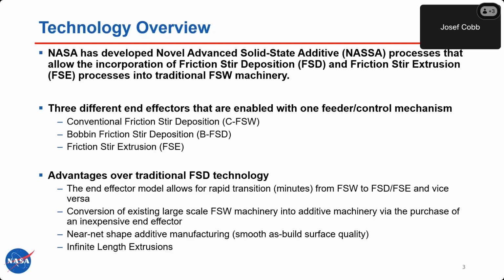The end effector model allows for rapid transition, like I was saying earlier, in really just minutes, from friction stir welding to friction stir deposition and vice versa. You can convert your existing friction stir welding machinery. And if you have large scale friction stir welding machinery, you can do large scale friction stir deposition just with the end effector. And the end effector can go on any of those machines, right? You just need to build an adapter plate to bolt it to, and you can go on any friction stir welding machine that you have.